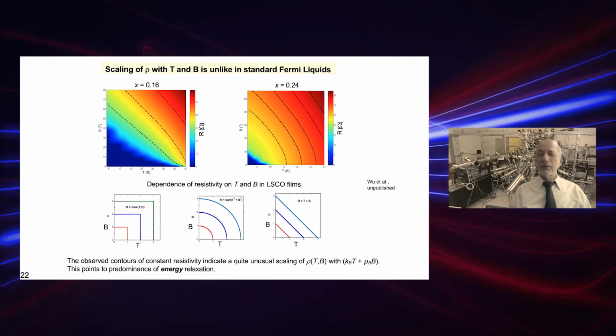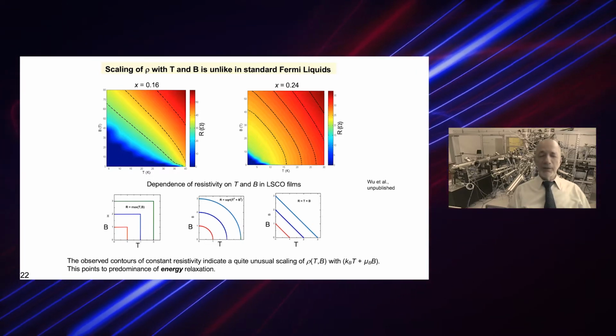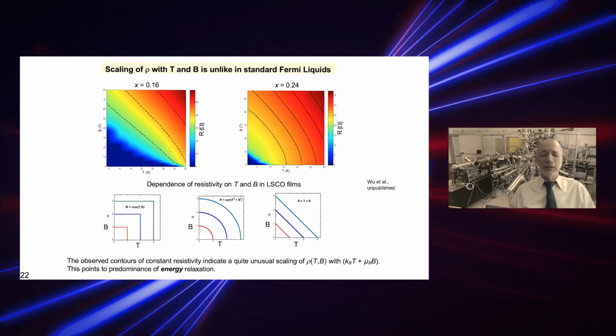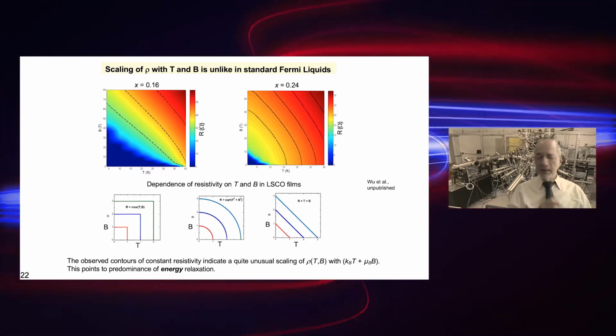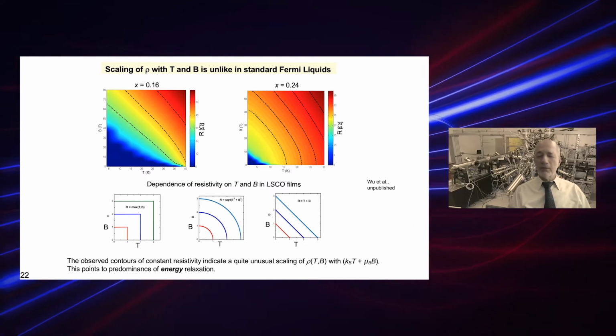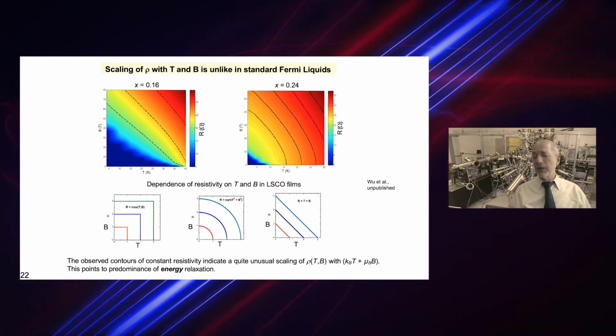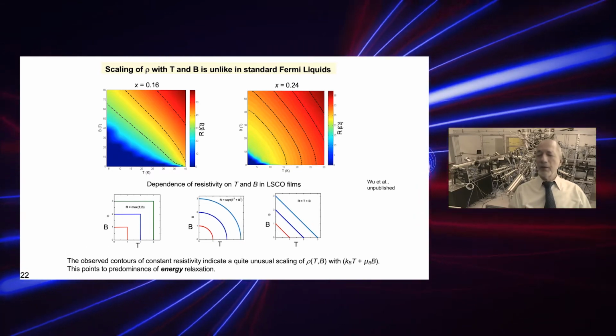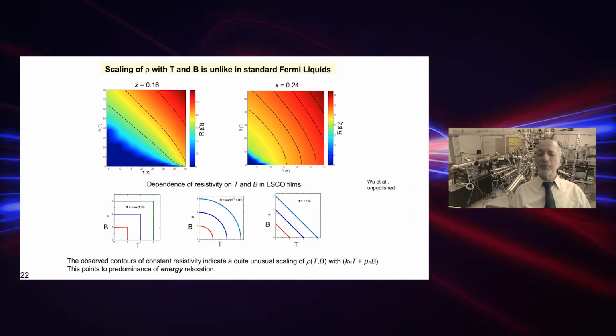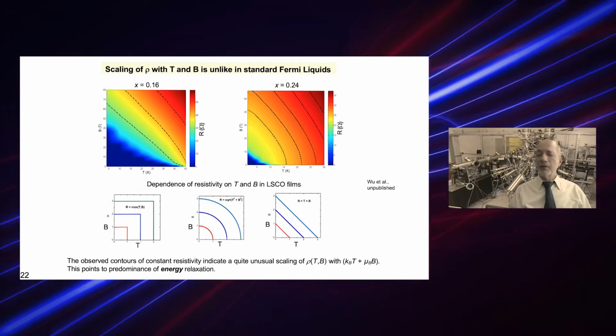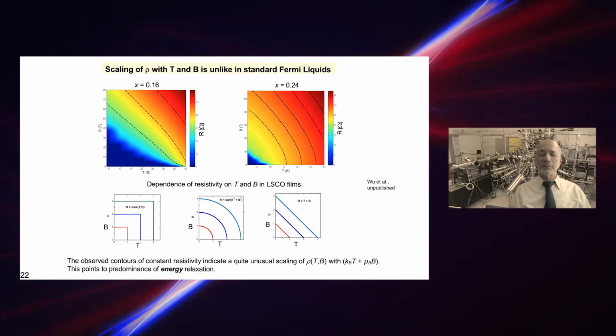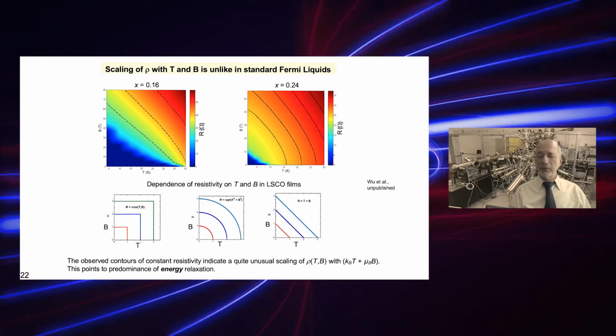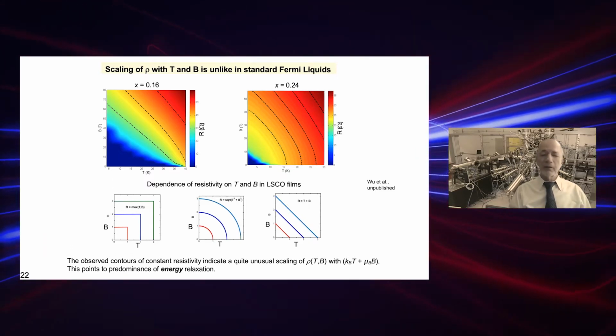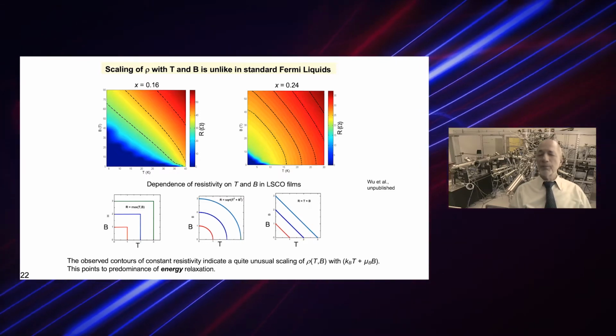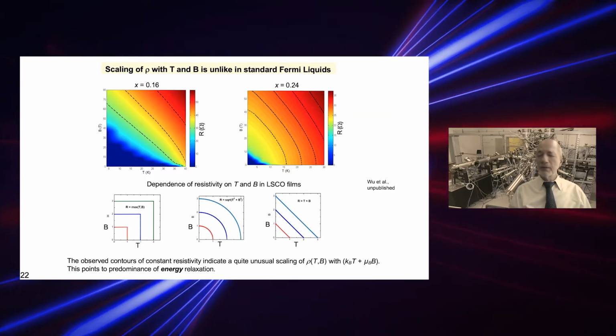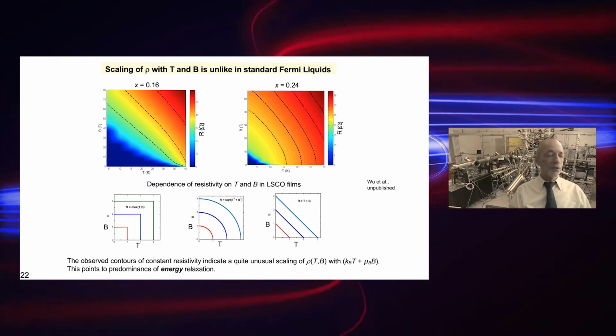That has several implications. One is that it looks like it is the energy relaxation that is relevant. So when you add frequency, you would expect also to add plus h nu. The second one is that the magnetic terms look like Zeeman, not like orbital effect. So it looks like a spin effect. And that is also supported by some observations that there doesn't seem to be dependence on the rotation of the magnetic field.